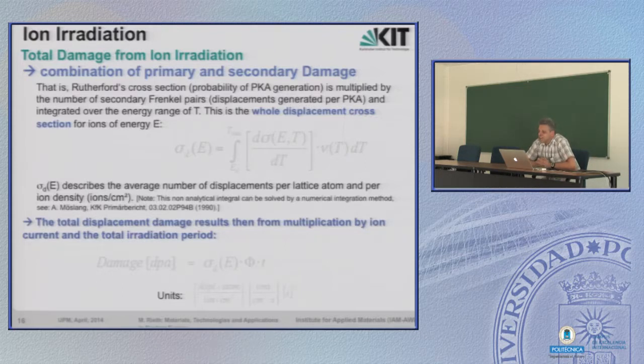Total damage from this ion irradiation. Now, to calculate primary and secondary damage, we have to combine both stages. That is the Rutherford cross-section, which was describing the primary damage, and also the number, nu, of produced Frenkel pairs. And the whole displacement cross-section, that's sigma_d, as it's called. Can you read it? Because it's light gray. Okay. We have to perform an integration starting from the threshold energy over the whole PKA spectrum, up to the maximum energy, which was in the range of 100 keV. Then the Rutherford cross-section multiplied with the number of produced Frenkel pairs, integrated over the whole range of the PKA spectrum, gives us the displacement cross-section.